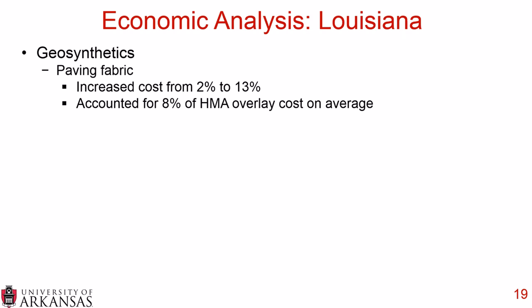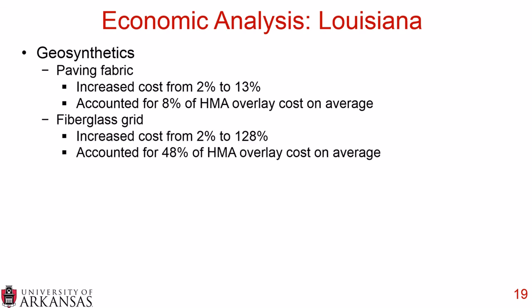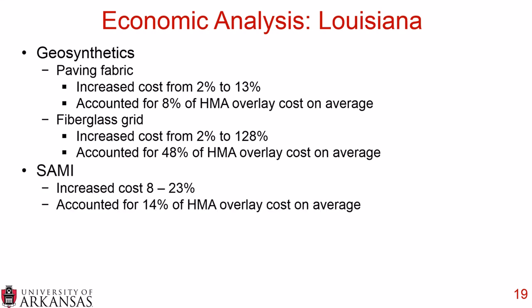Now, after they had gone through all those performance analyses, they did a very comprehensive economic analysis. So they found that for paving fabrics, they increased the costs from anywhere from 2 to 13% of the projects, and they account for approximately 8% of the hot mix asphalt overlay cost on average. The fiberglass grids increased the cost anywhere from 2 to 128%, and on average, it accounted for 48% of the overlay cost. The SAMIs increased the cost anywhere from 8 to 23%, and it accounted for approximately 14% of the HMA overlay cost on average.